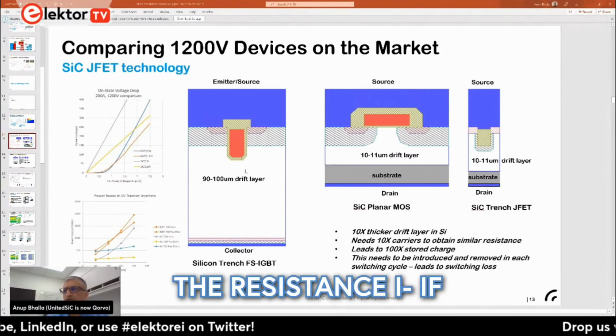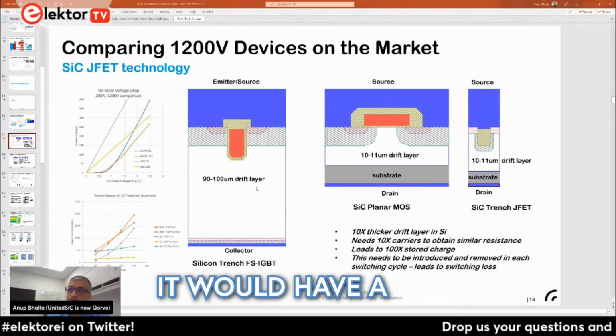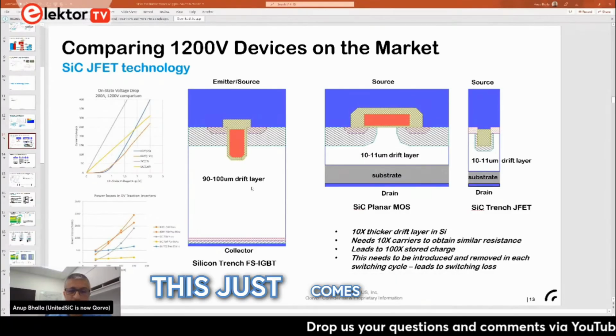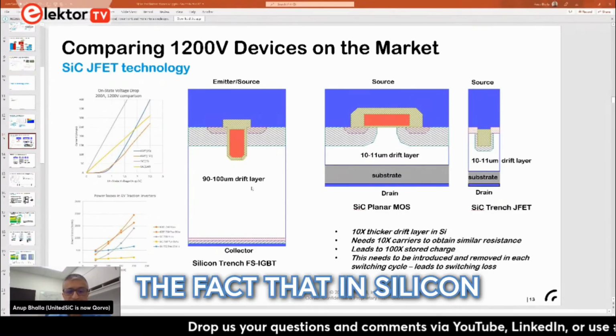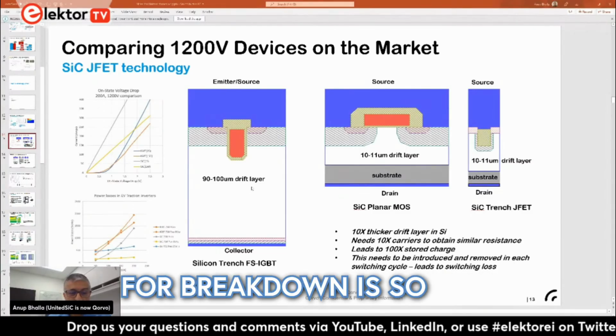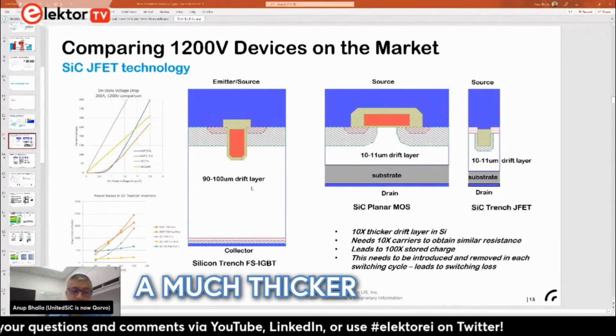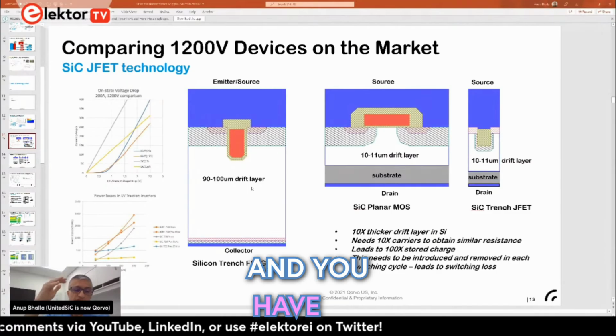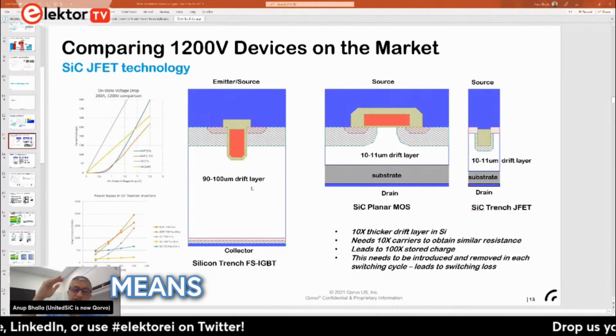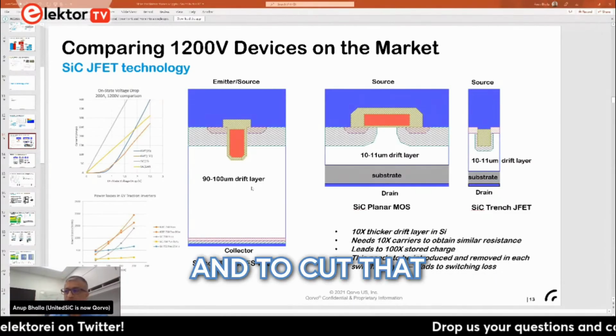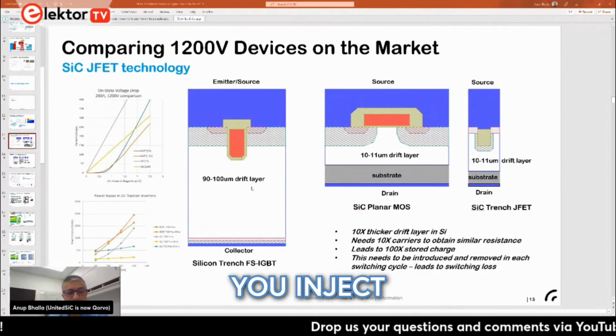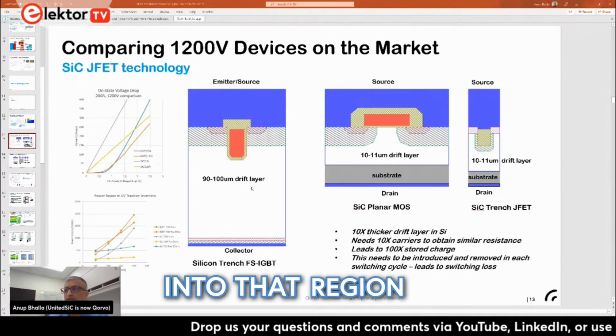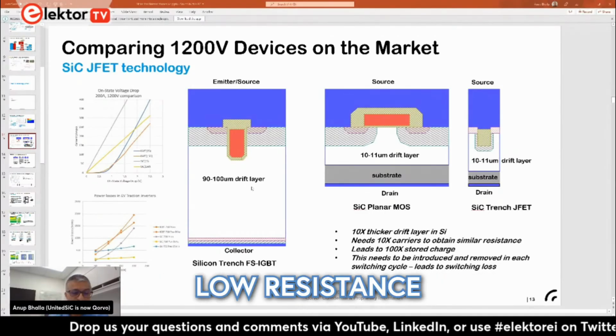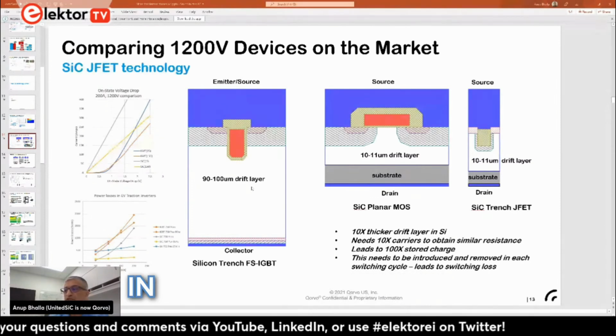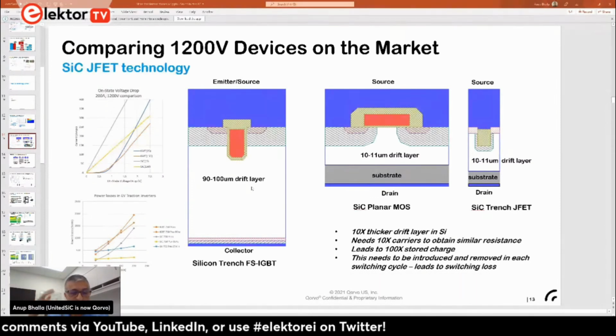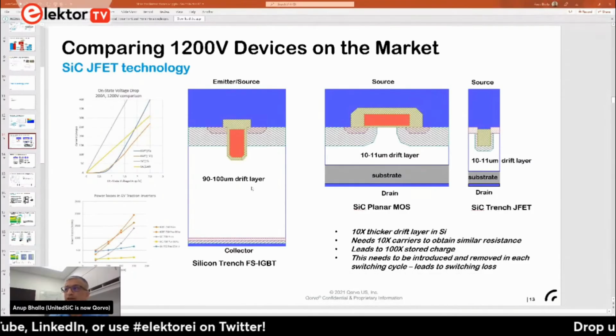the resistance, if we try to make a MOSFET at 1200 volt, it would have a very, very high resistance. This just comes from the fact that in silicon, because the critical field for breakdown is so low, you have to use a much thicker voltage supporting region, and you have to dope it lightly, which means its resistance tends to be high. And to cut that resistance, the technique is you inject electrons and holes into that region so that it'll have a low resistance. But then once you do that, in every switching cycle, you've got to move the charges in and out, right? Which ends up slowing down the IGBTs.